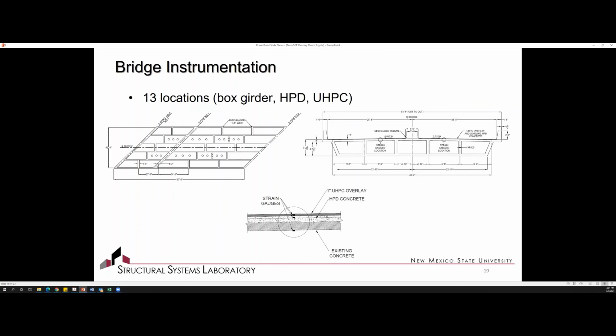Currently, we have 13 locations in each of those different locations, and you can see here, we took the cells and identified which cells we thought were going to be best for monitoring, to give us the results we were looking for on shrinkage, temperature effects, and so forth. So this is where we've chosen these locations, which you can see in circles on the plan view, and then looking at the cross-sectional view, you can see that we chose the interior boxes for the monitoring as well.